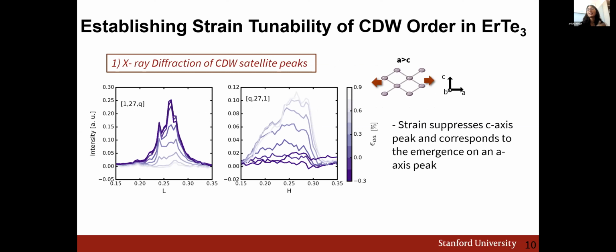All right, so on this slide, I'm just showing measurements of the CDW superlattice peaks that were done in the material while different values of uniaxial strain were applied. For all the measurements I'm going to be showing today, we're going to be talking about strain applied to the A-axis of the material. So in this case, we're applying tensile strains to the A-axis, which effectively is reversing the inbuilt anisotropy of the system. Starting with the darkest curves on this plot, we see a CDW superlattice peak along the L direction and nothing along the H direction, which is exactly what we'd expect, consistent with the CDW order being along the C axis.